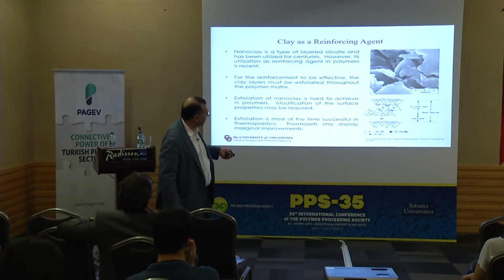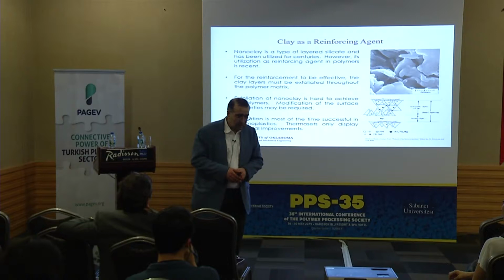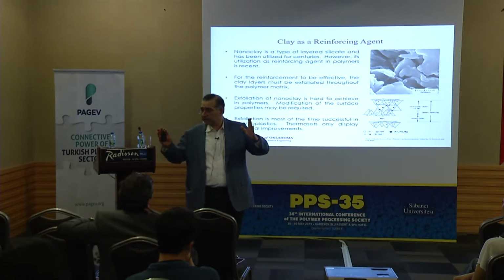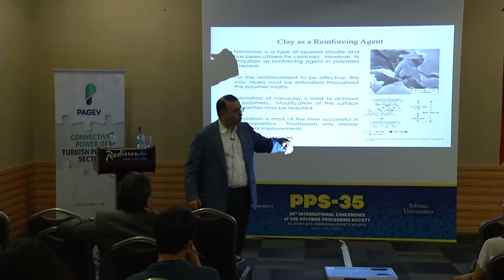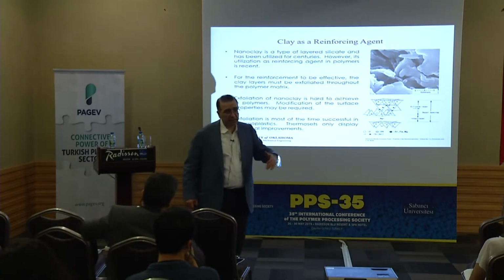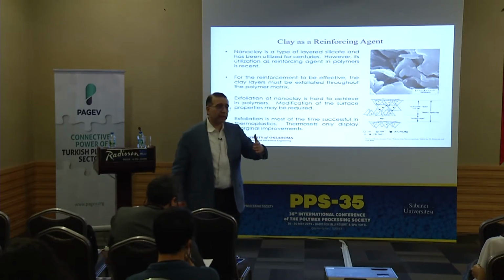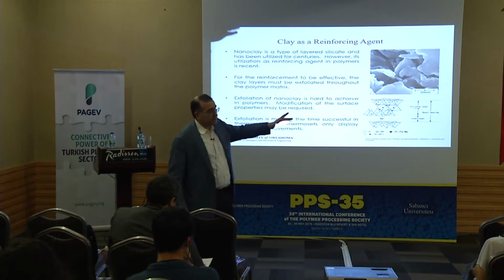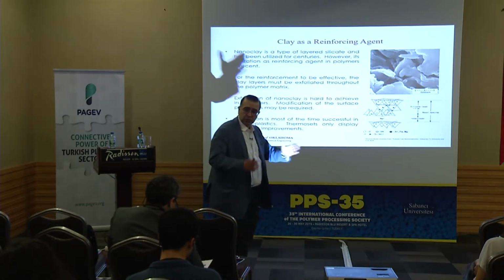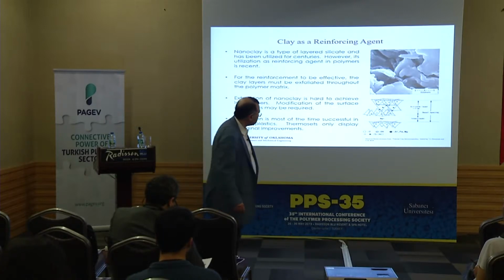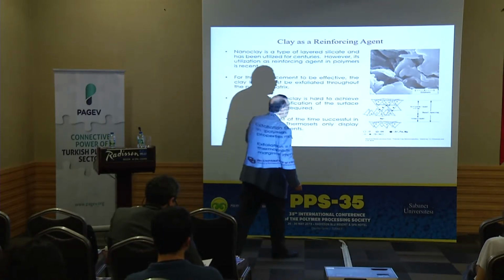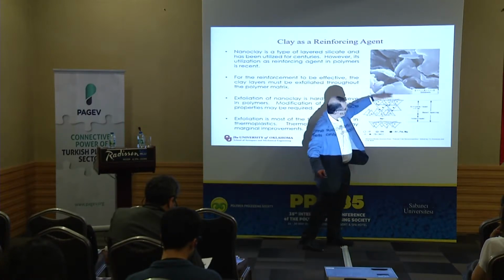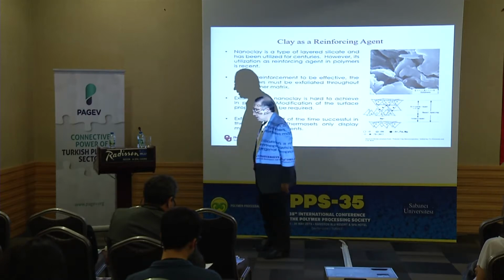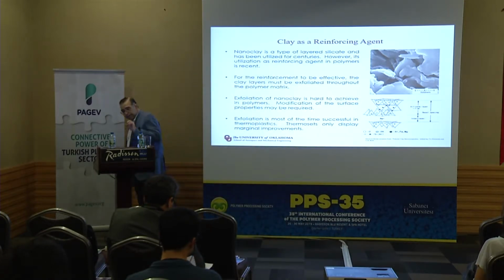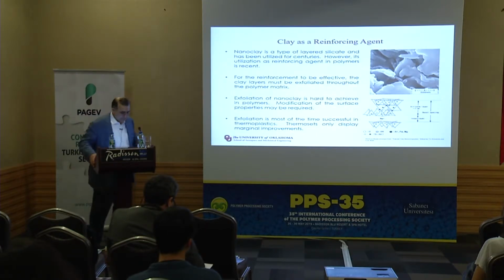So what people have done is they chemically change the surface chemistry of this silica clay and try to separate the spacing. Those materials are called organoclays. You can buy maybe half a dozen or a dozen different types of organoclays with different basal spacing, and they verify it using X-ray diffraction, so that you can determine what the spacing is. The whole idea is to separate these layers from each other so that you can have the polymer diffuse into this. And it is called exfoliation.